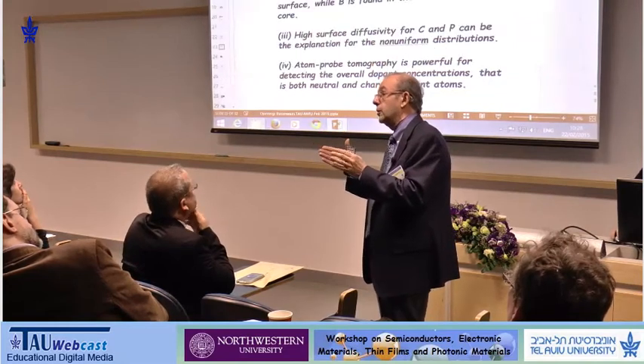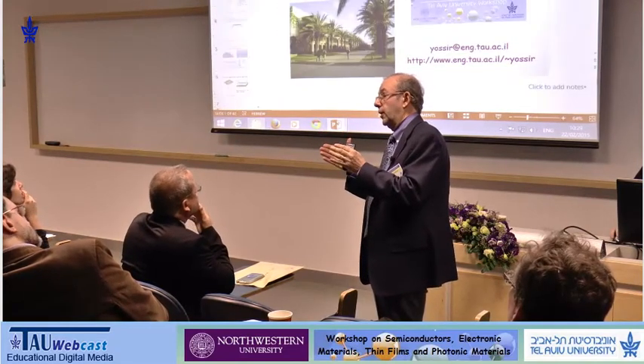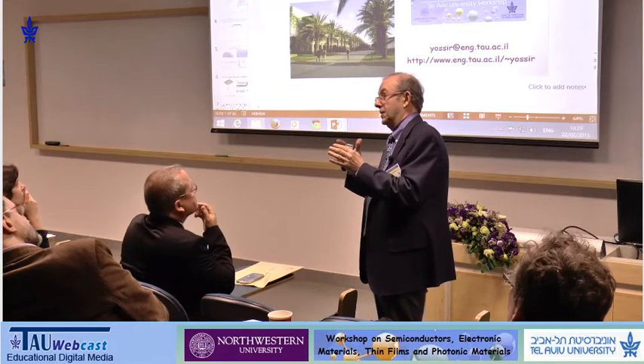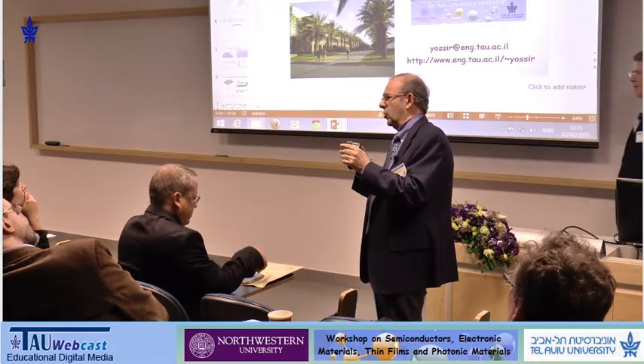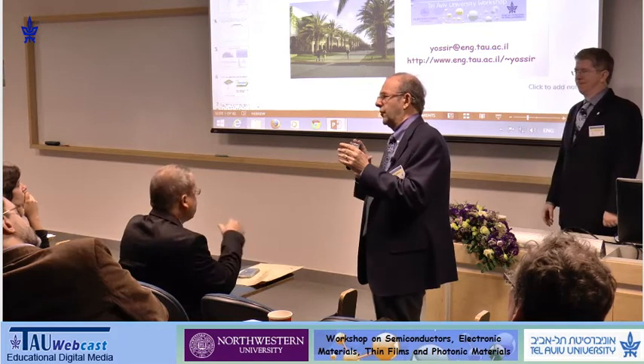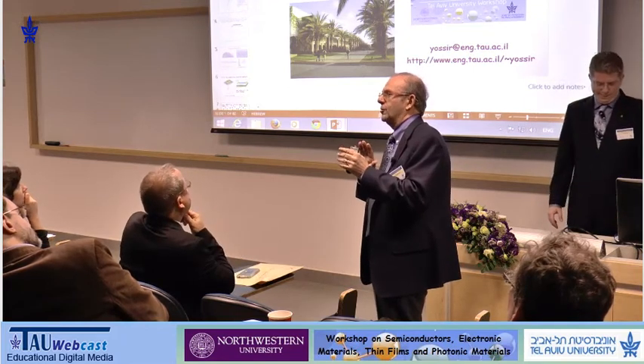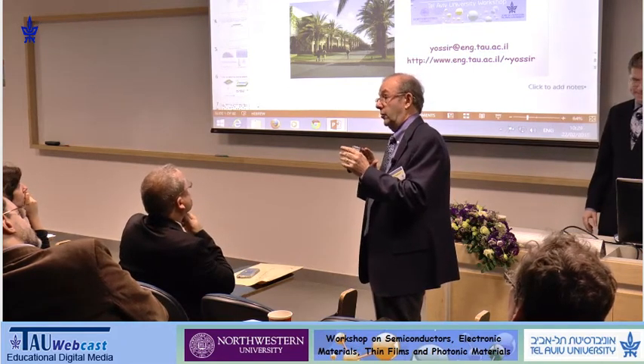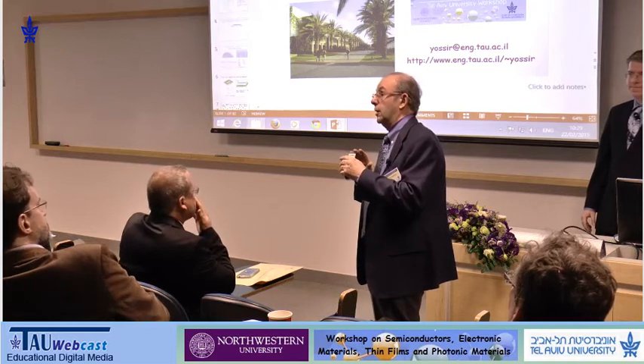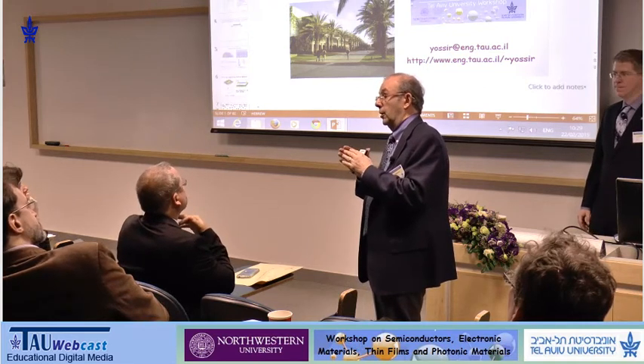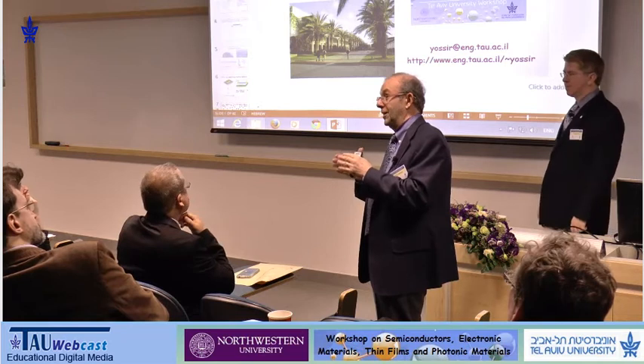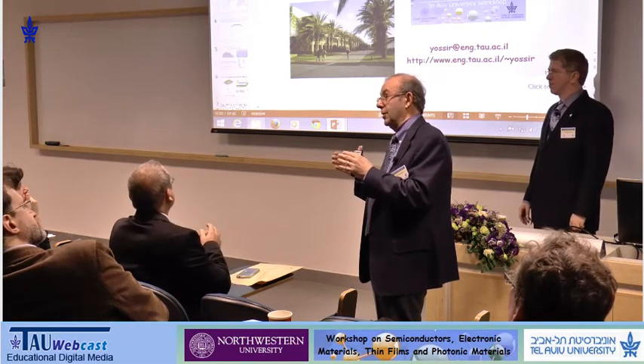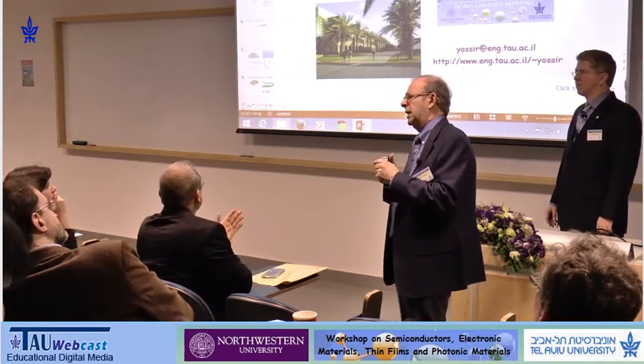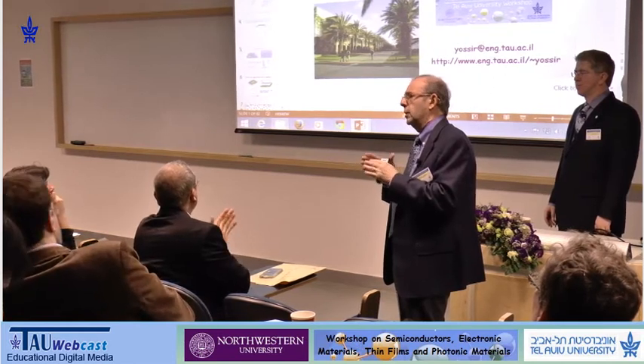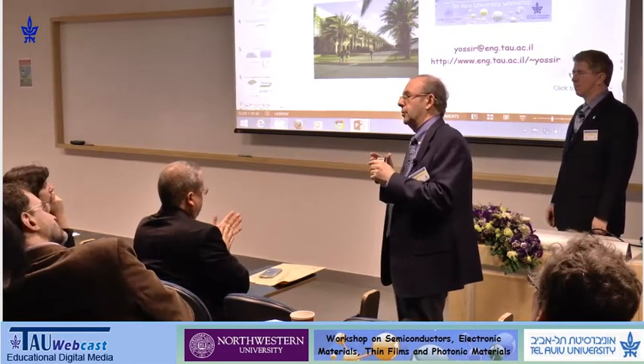So it's an artifact. It's an artifact of the technique, but it's not an artifact of the preparation. I mean, we've seen this in other materials, too. It's not the first time, so it wasn't a surprise to us. It happens even in metallic alloys, where we know, say, from TEM, how thick it should be, and it's always somewhat broader. And the amount of broadening is material dependent.